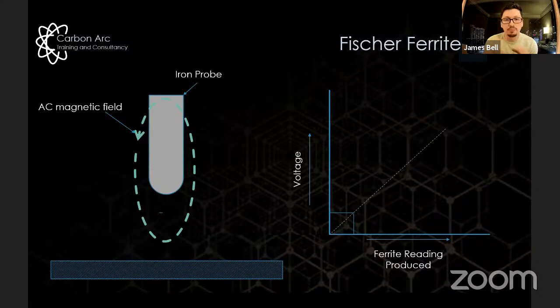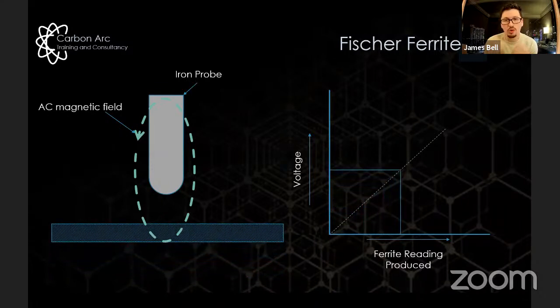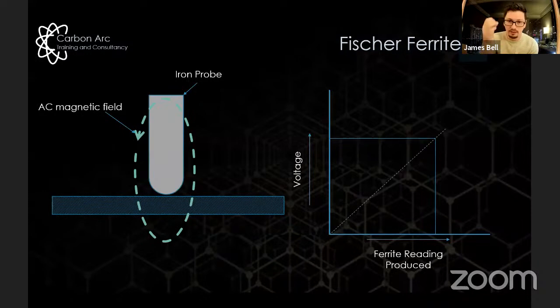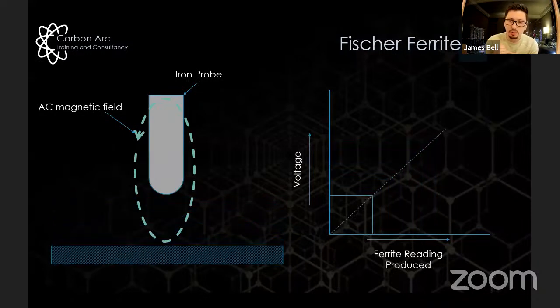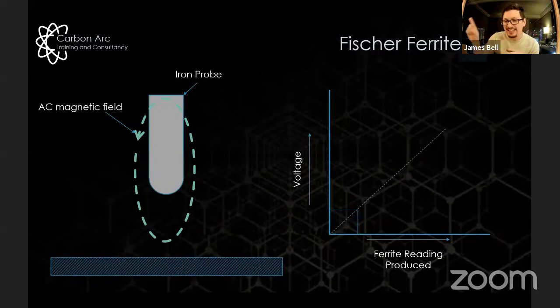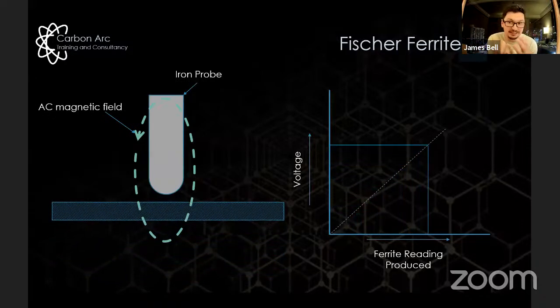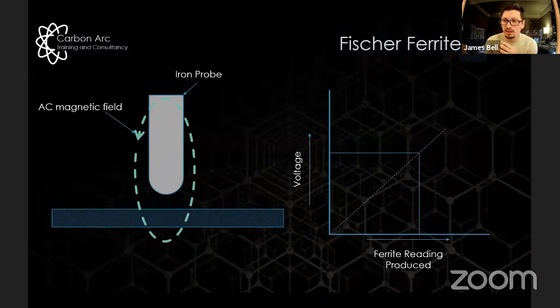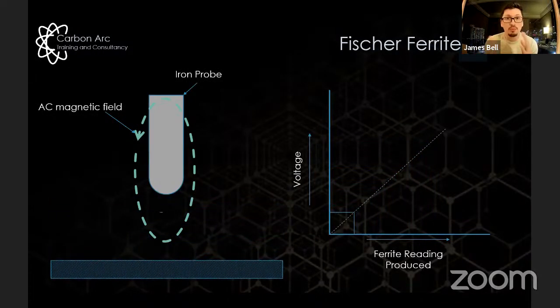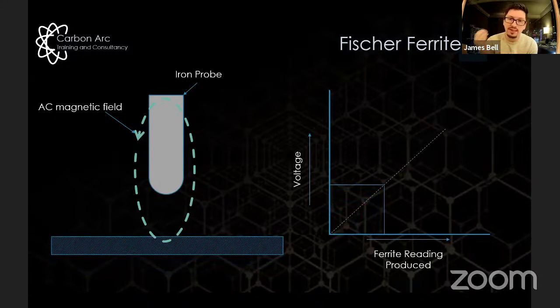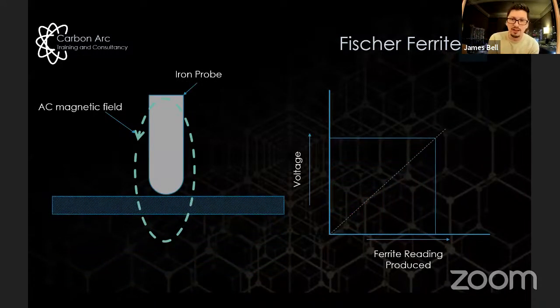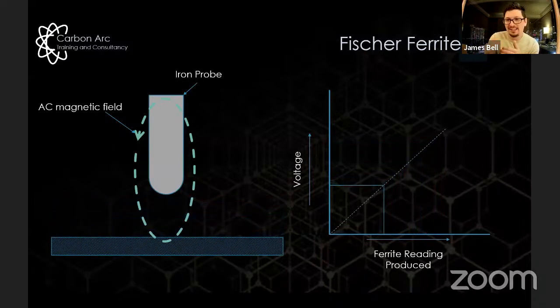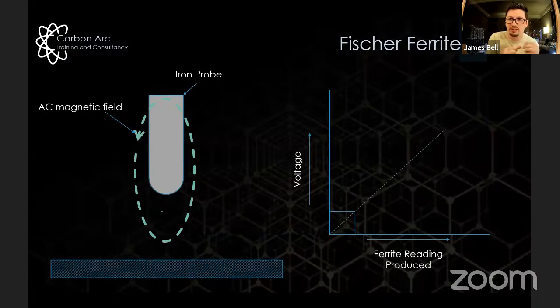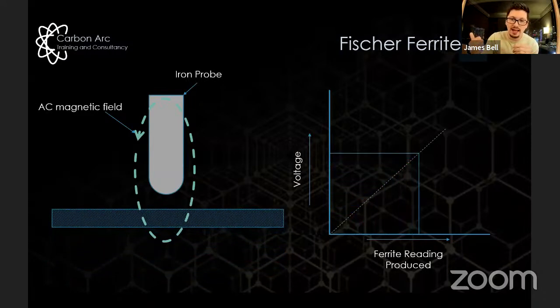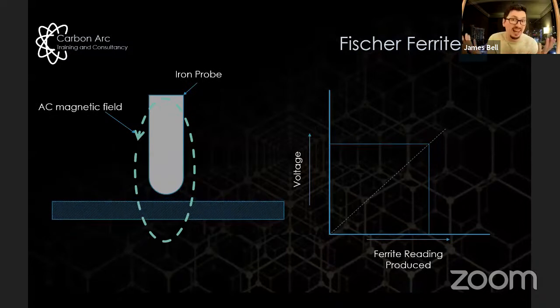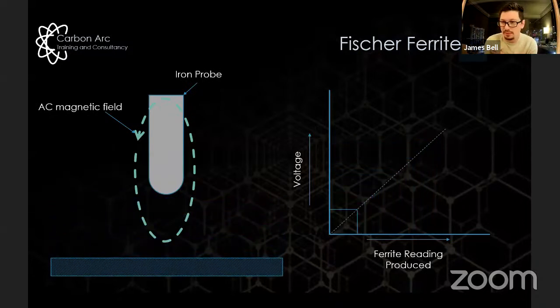And the way we calibrate that machine is to take a known ferrite sample, touch the probe on the surface of it, and set a reading of the magnetism to a percentage value. And that's how it works when we use it in production. We're going to take the probe, touch the sample, and it's going to compare the reading we made during the qualification test to whether it is greater or less than that value, and what percentage it would be.